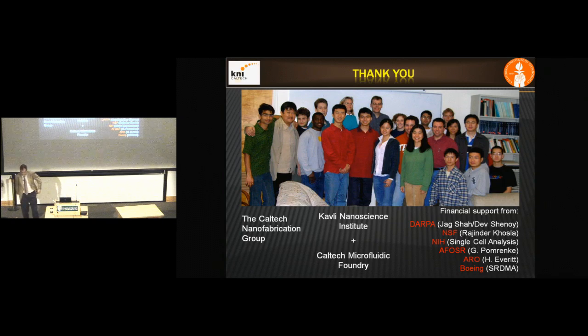When you're making these very small structures, what does it take to build the mask that you use to make them? Ah, yes. When we go to the smallest structures, what do we use to make the mask? Well, we use electron beam lithography in my lab because that's convenient for us. We don't have a projection mask aligner with a 22 nanometer resolution. However, in commercial approaches, and the 32 nanometer node, and now more recently the 22 nanometer node, it's all done optically by using what's called phase shift masks. Now, the masks are pretty expensive. They cost maybe $50,000 or so, or upwards from that, because they have dielectrics to make sure that your intensity on your sample is optimized.